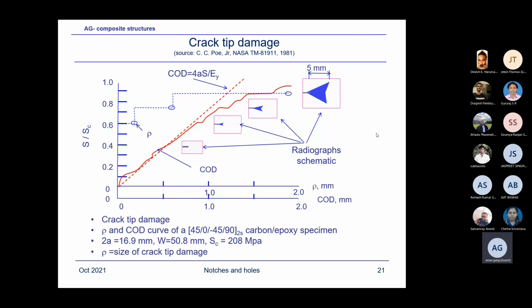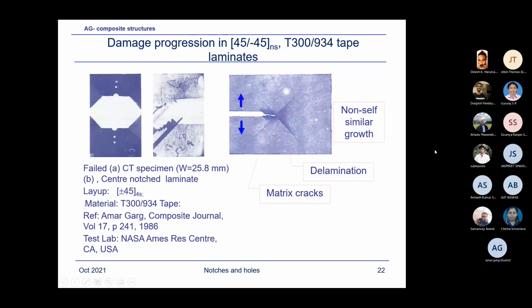And actually, I'm showing some actual pictures from my papers, which I had done at NASA while investigating the fracture damage propagation. You can see here, this is a central crack coupon, and this one is a compact tension coupon. I used all sorts of coupons, in fact, to investigate the fracture behavior. And the layup for this one is plus minus 45. So when we started loading, you can see here, this is the original crack tip. And then there's a matrix crack, that is 45-degree ply cracking, and the other 45 on the other side will be cracking. And you find lots of damage.